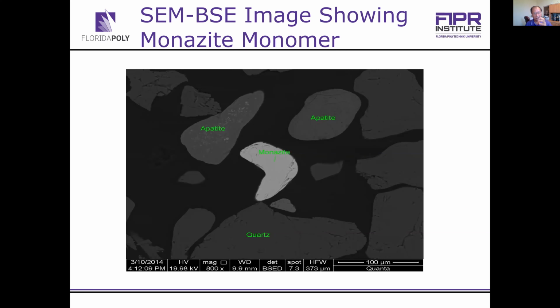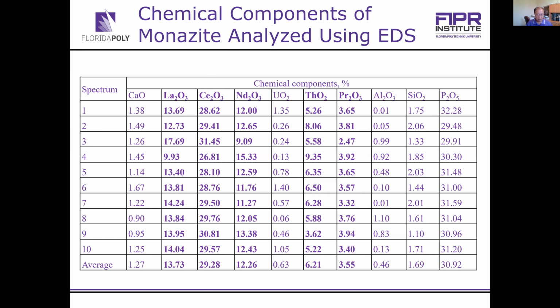So SEM analysis did find some particles, like monazite particles, as you can see from this slide. There are obviously clear, separate monazite particles in the flotation tailings. This is an analysis of the monazite particles using EDS to actually determine the concentration of the monazite particle. As you can see, it contains various rare earth elements, including lanthanum, cerium, neodymium, thorium, and uranium.